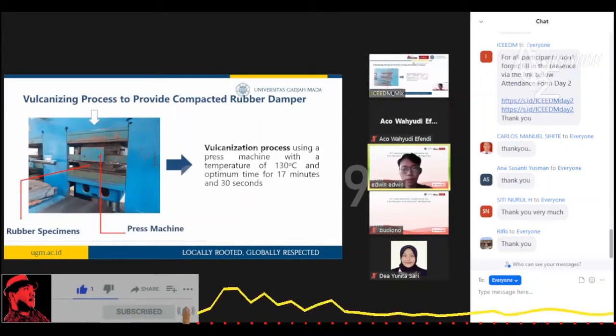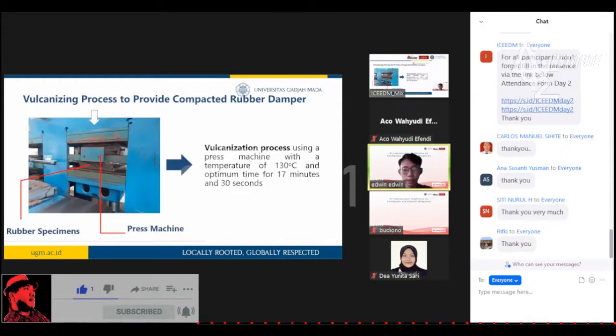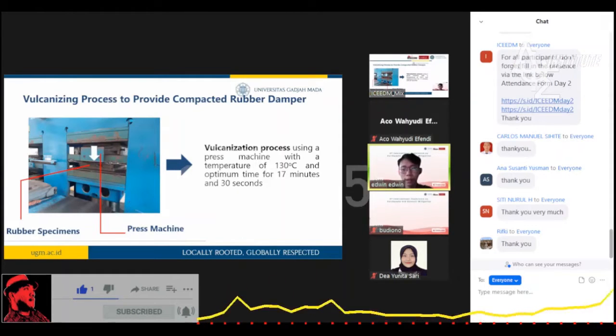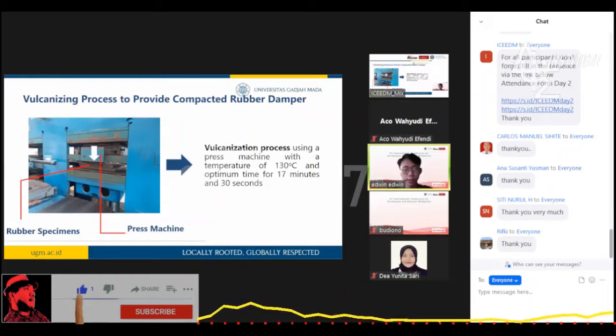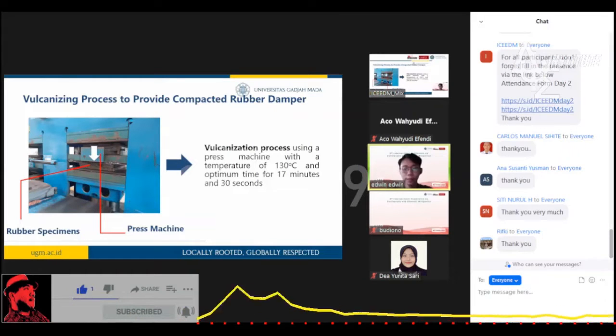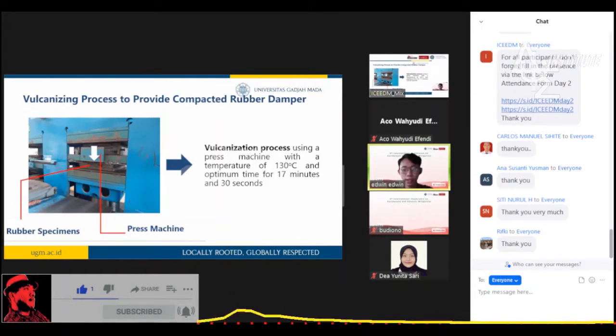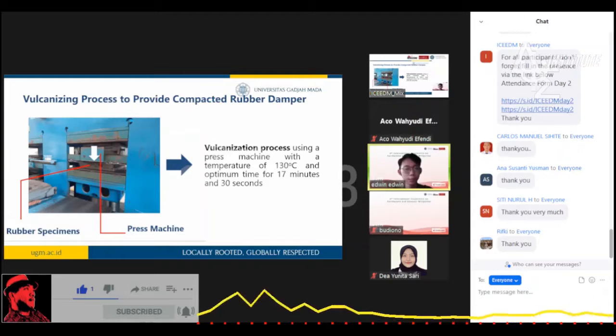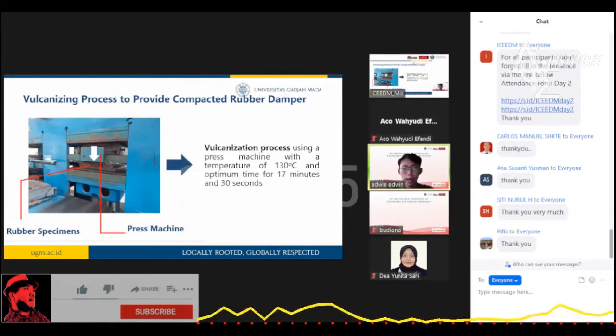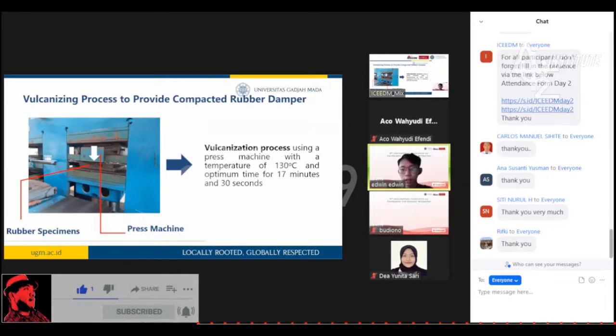The last step was the vulcanization process using a press machine. The time and temperature used in this vulcanization process was the same that we get from the rheology test. The vulcanization process was done with a temperature of 130 centigrade and time for 17 minutes and 30 seconds.